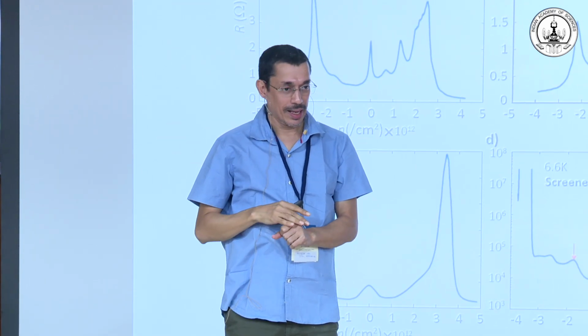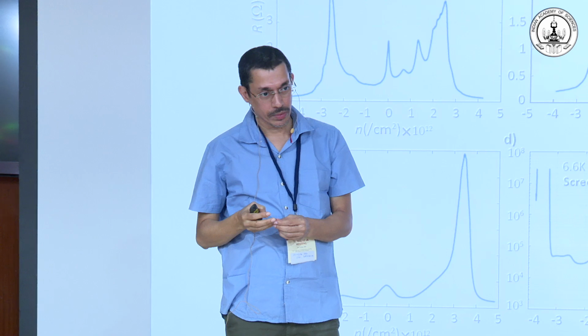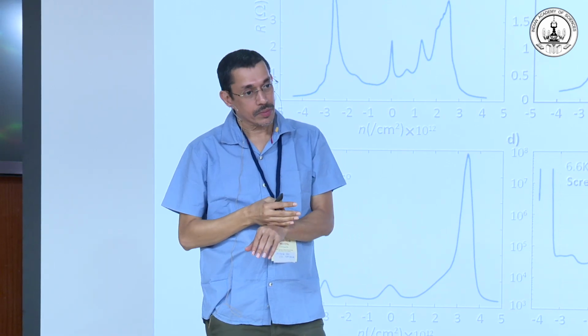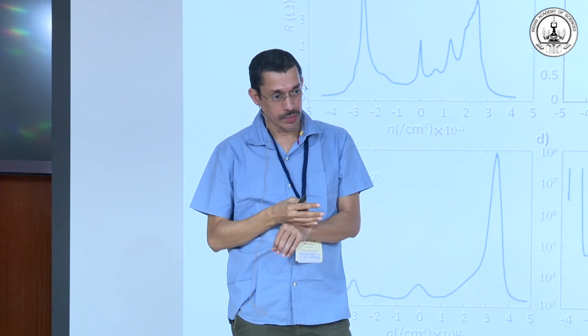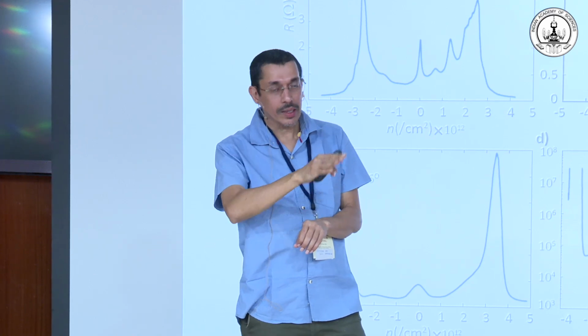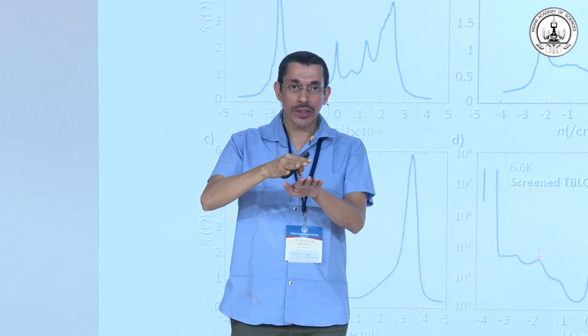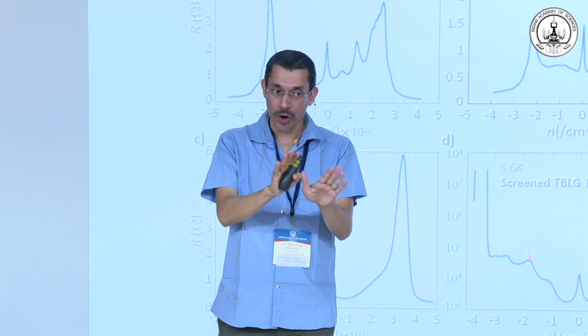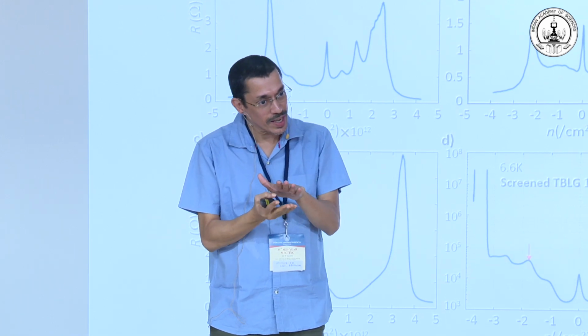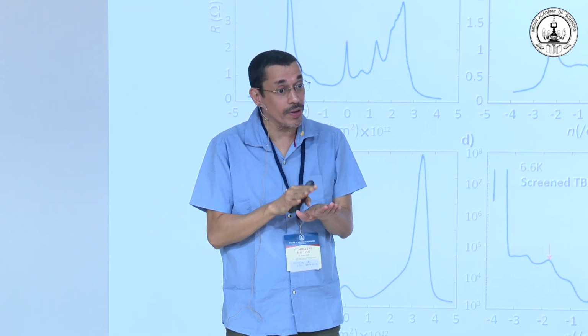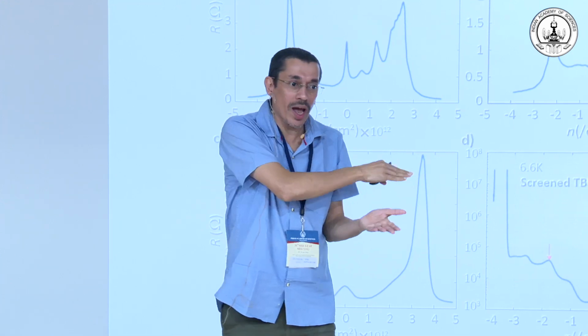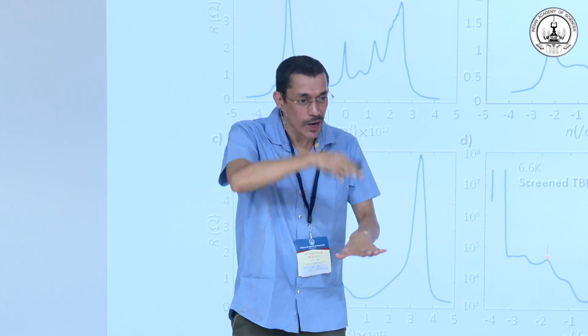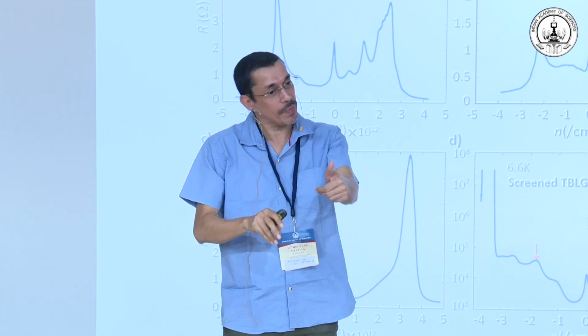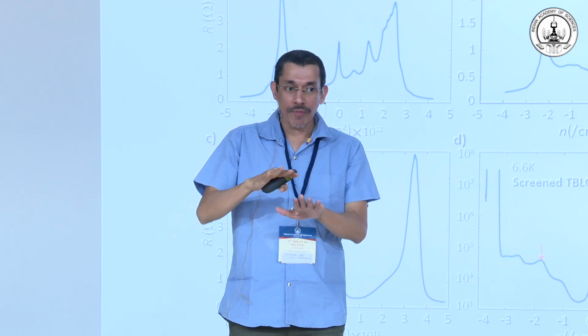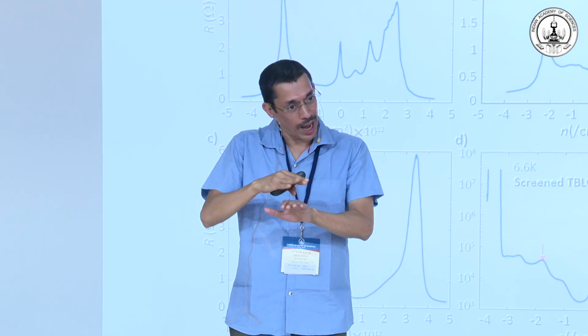Why does, like you said, your devices were unstable when you formed them? Yeah. But once you made your contacts, your devices became stable. Right. So what do you attribute that to? Right. So first of all, once the device is being made, there is some heating involved. Indeed, there's some 50, 60 degrees centigrade temperature involved, and that we feel is a culprit, because that is required because of the technical details. Otherwise, you cannot do all this pickup technique. So some heat up is required. So that 50, 60 degrees actually helps them to relax.